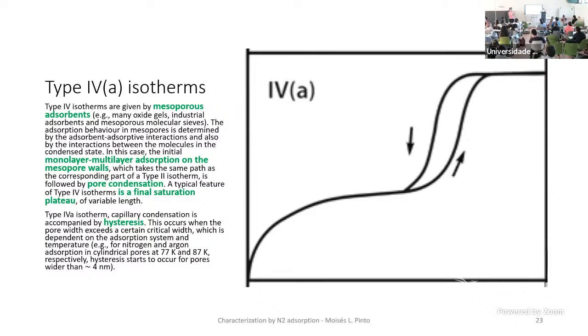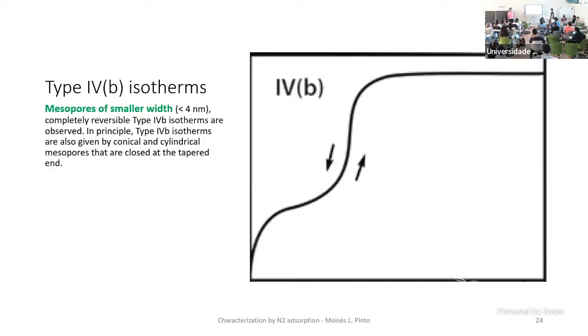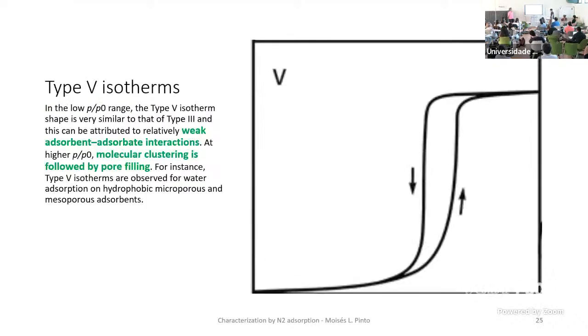But the desorption does not proceed like this. It proceeds like emptying, like this. Yes? So you usually need lower pressure to desorb. Yes? So the type 4 that you see in here is the same, but you don't have hysteresis. Usually if you have something like this, it's because the pores are below 4 nanometers. And the type 5 isotherm is similar to the type 3, but then you have condensation in between the particles like this.